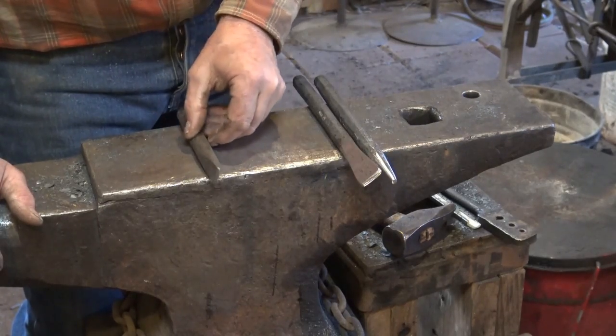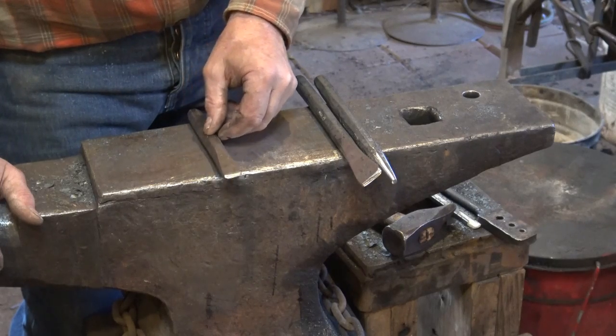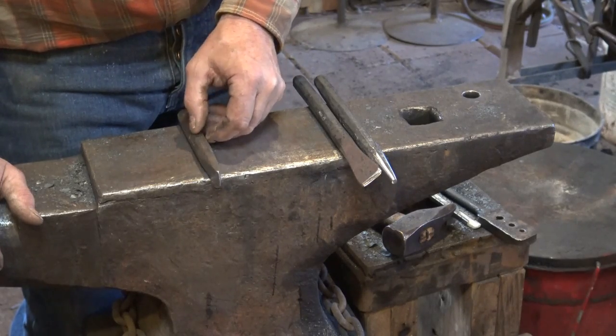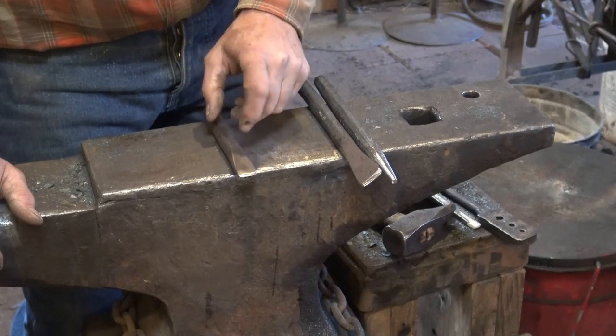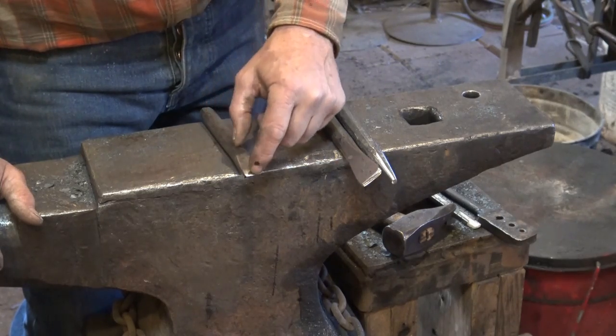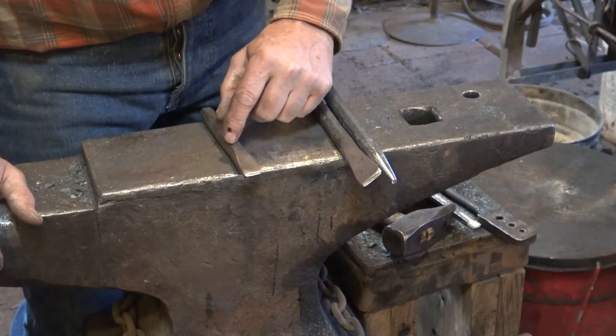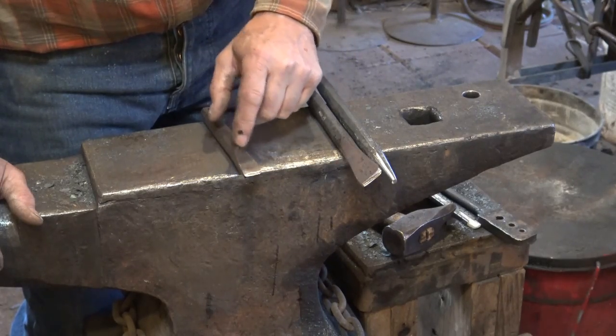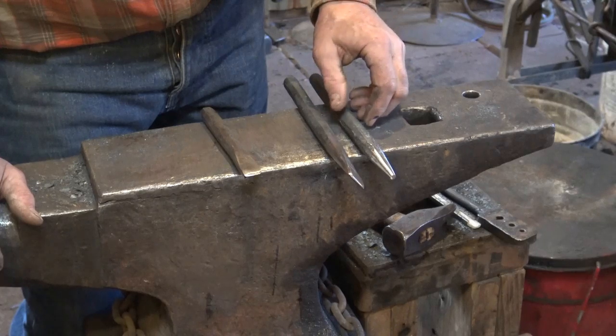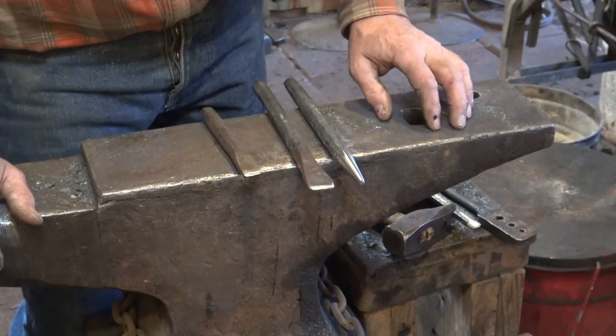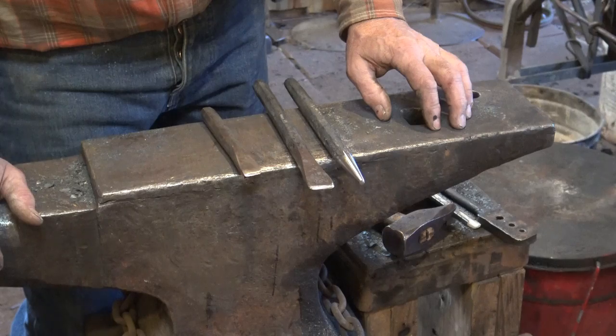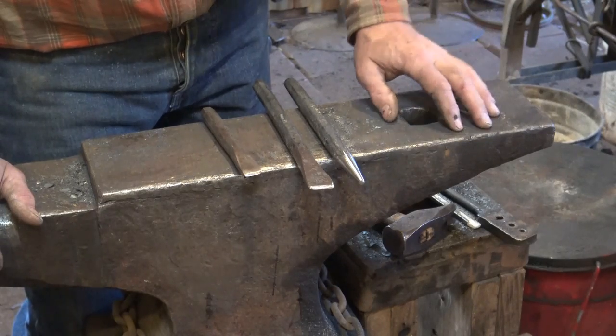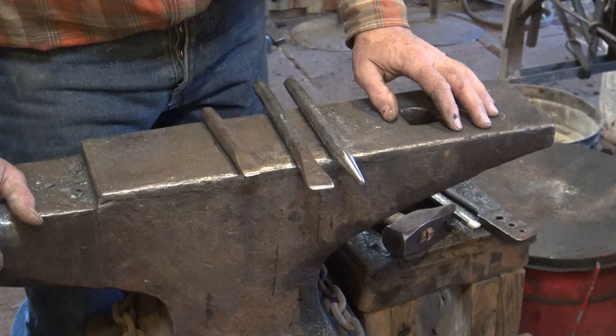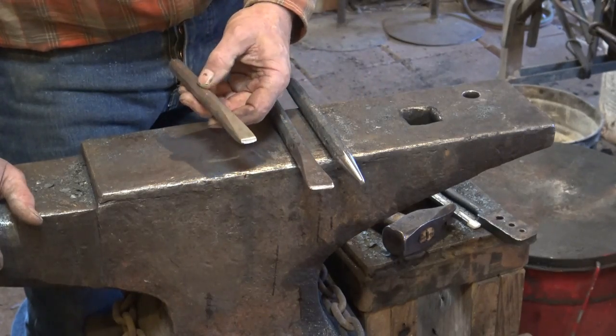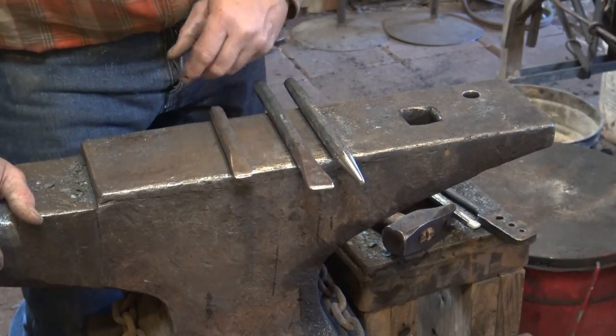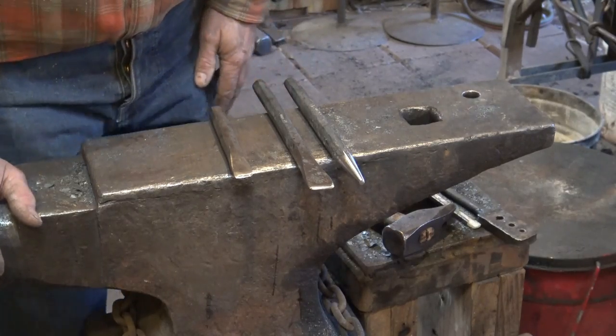The cold chisel, on the other hand, is going to work cold metal, and it has to be hardened. So that's a pretty important tool to harden. All of these we can harden a bit of it and let the colors bleed for tempering, and we may do that with one of them. But in the long run, I prefer to just put them in the little toaster oven and guarantee I get them to the right temperature all the way through. They can soak, and it lets me go on to something else while they're tempering instead of standing here watching them.